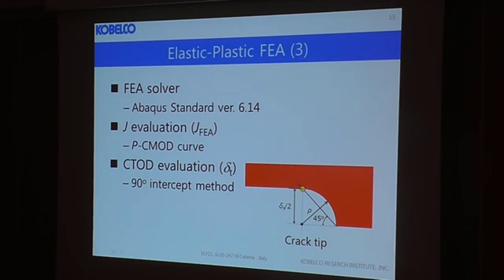Abaqus was used as the FEA solver. The JFEA was evaluated using the relationship between load and crack mouth opening displacement based on ASTM E1921. The CTOD was calculated by means of the 90 degrees intercept method.